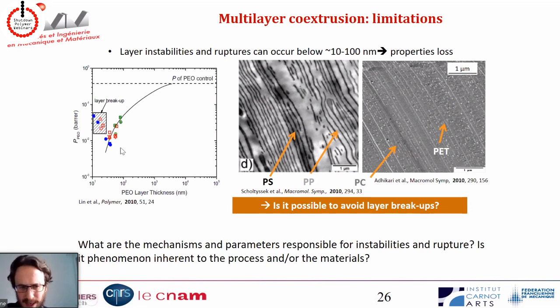And why does it come up again? It's because the layer breaks. So if you look at that under a microscope, you will see things like that. So the layers are broken, and because the layers are broken, the gas can easily find its way through the material, goes from one way to the other, and the permeability goes up. And because these instabilities and layer breakups were observed in so many systems, we tried to understand the reason why. Is it a physical reason? Is it controlled by a parameter? Can we have some knowledge about that?